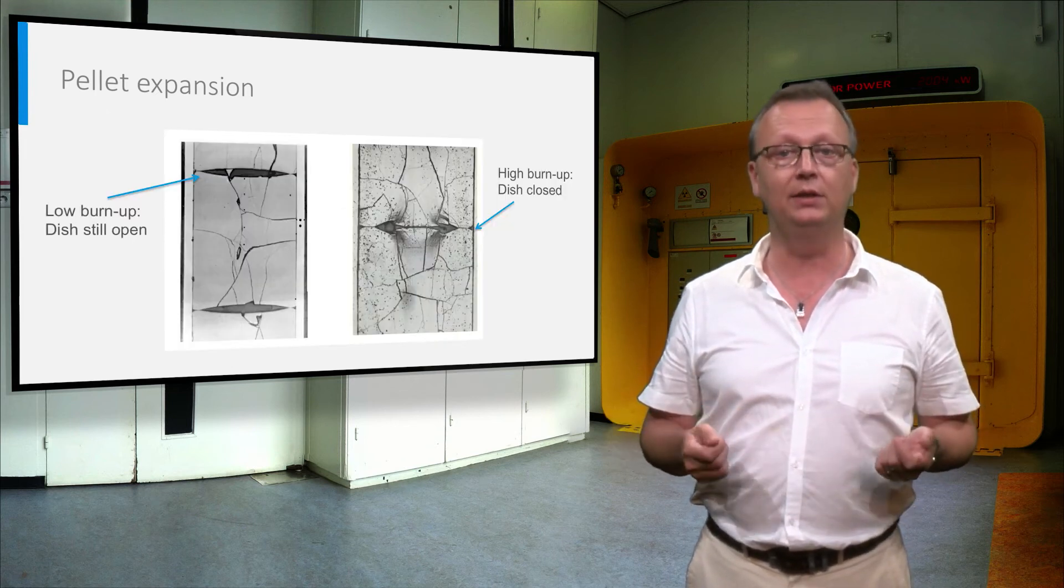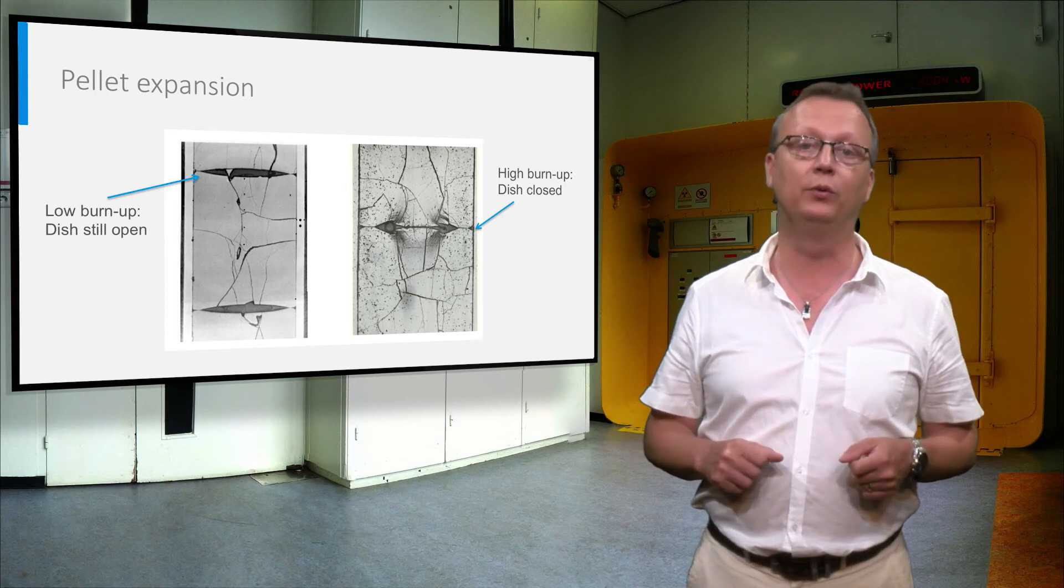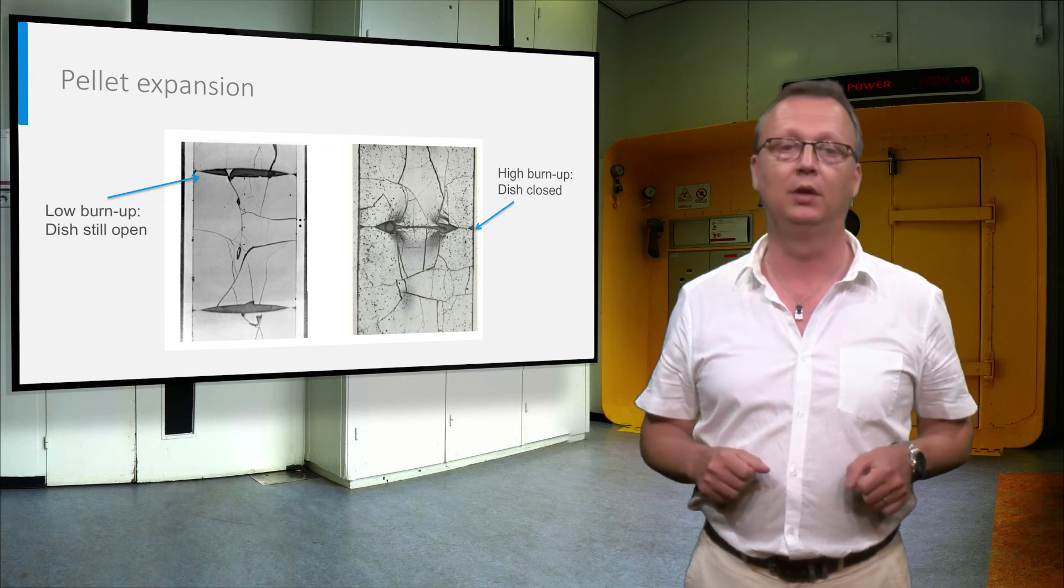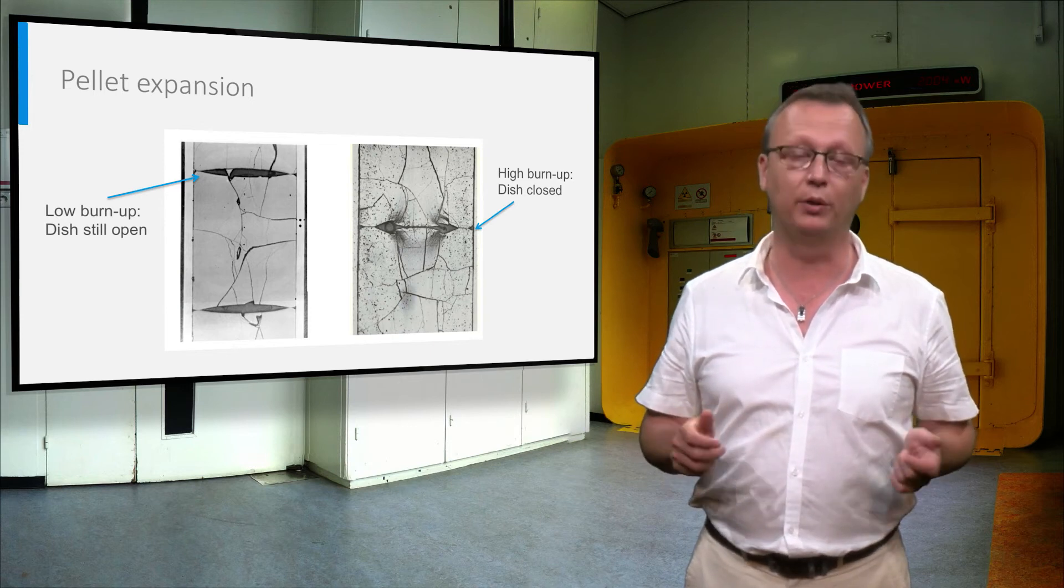This can be very nicely seen in this picture of irradiated fuel of low and high burn-up, the low burn-up fuel still having an open dish, whereas it is closed in the high burn-up fuel.